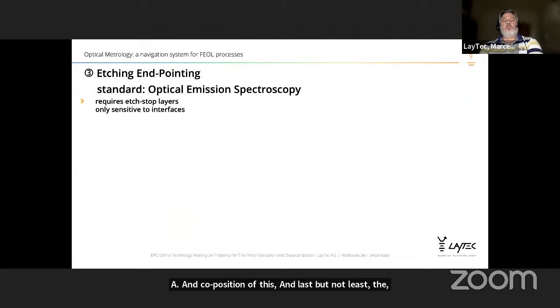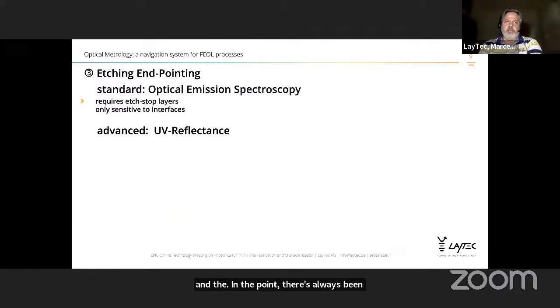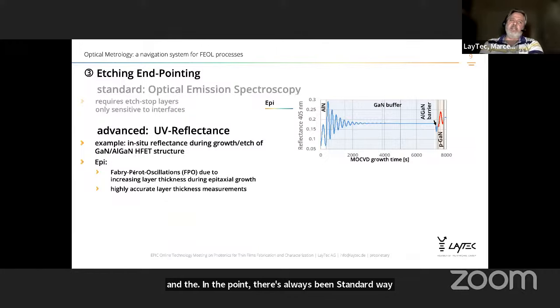The standard way would be to do optical emission spectroscopy, but this requires etch-stop layers, and it is only sensitive to the interfaces. Again, we are using an advanced approach with the UV reflectance, and an example is shown here on the right. This is the reflectogram that you would measure during the growth of this HEMT device. So you see that there is the oscillation of around 5 nanometers because of the material that's absorbing the light, and then you get the AlGaN barrier, which has a different extinction coefficient, and then again you can single out very accurately the pGaN material here.